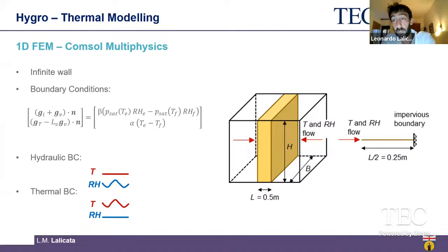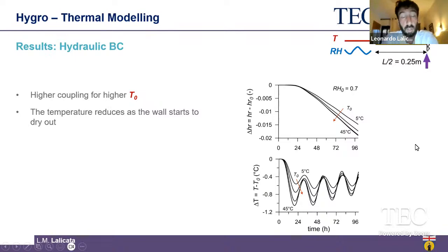The results I'm going to show you next will all refer to the center of the model, so the impervious boundary here. And let's now have a look at these results. So these are the results from the hydraulic boundary conditions in which the temperature has been kept constant and the relative humidity changes. What happens is that at this point here, after one point, the wall starts to dry. So there is a reduction in the relative humidity. And this is because the imposed perturbation is globally a drying process.